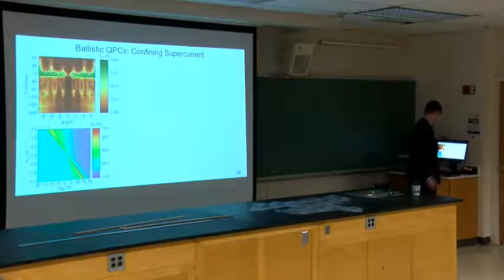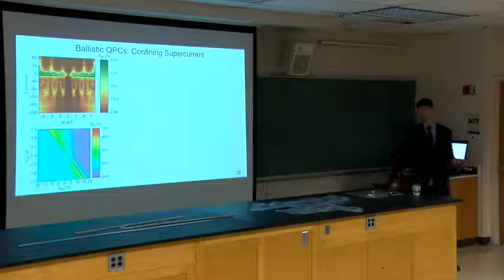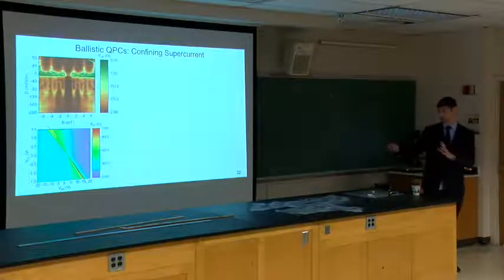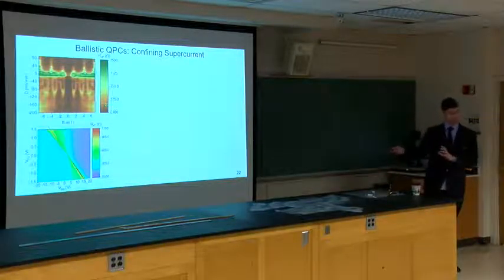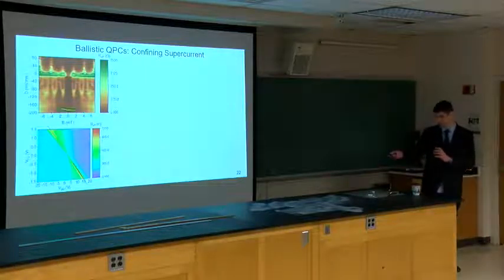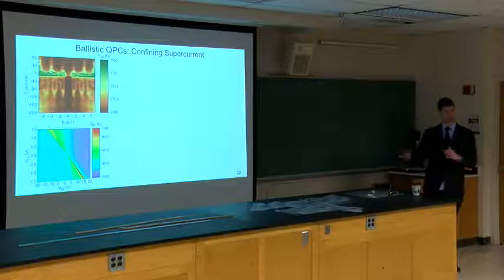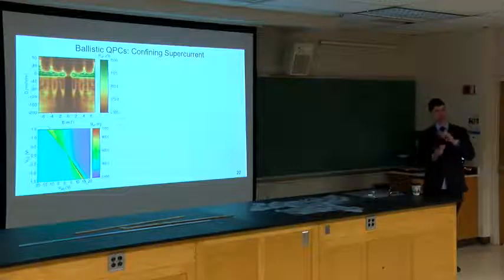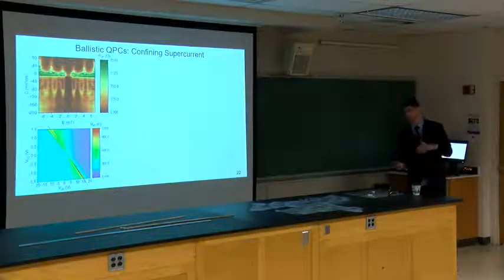So now we're going to look at the Fraunhofer patterns, like I mentioned before. I would recommend not looking at this because it'll be a little complicated until after I go through. This is the effect on the four-terminal resistance measured from the contacts of the device while changing the top gate and the back gate, so changing the electrostatic environment and inducing a displacement field across the device.